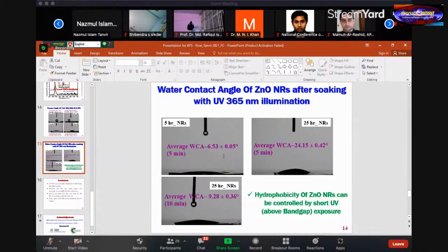So you have to go for measuring the thickness dependence of this hydrophobicity and hydrophilicity, and at the same time the cohesion and adhesion. Some stress develops between the substrate and the material coated, so there should be a matching of these two things for good adherence and coherency. So from the application point of view, there are more things to be done.